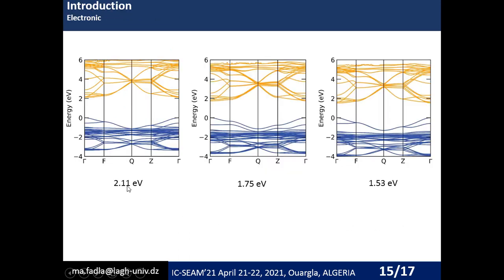We also calculate their band structure, and you can see we improve the band gap. For example, with 70% of lead, it is suitable for the perovskite-silicon tandem solar cell, and it is really suitable for the single junction solar cell. And you can see this compound has almost the same band structure.